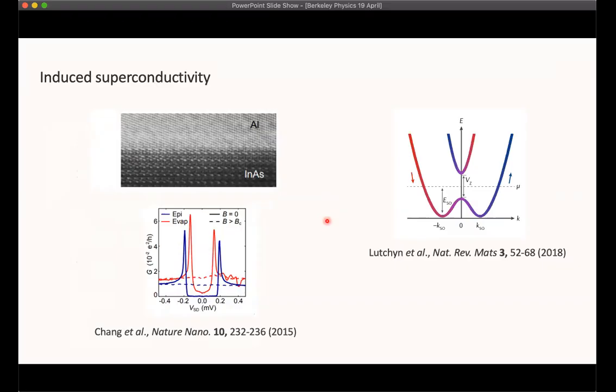Another of the ingredients, the induced superconductivity, is important to check because it's not enough just to lay down some superconductor on top of your semiconductor and hope for the best. In fact, the proximity effect and the strength of the induced superconductivity depends a lot on the quality of the interface between the superconductor, here's aluminum, and the semiconductor, indium arsenide. And this is a really nice example of the epitaxial growth of aluminum on indium arsenide.